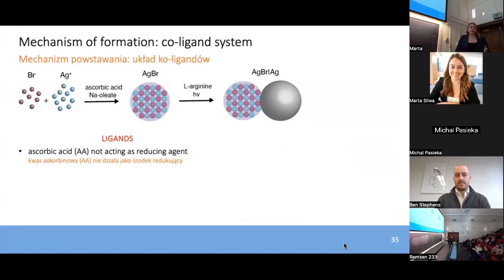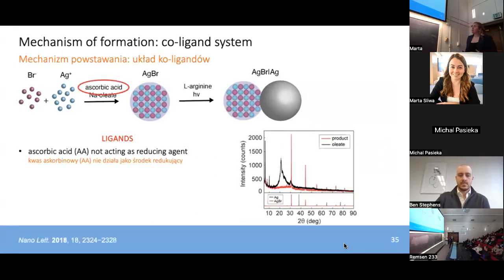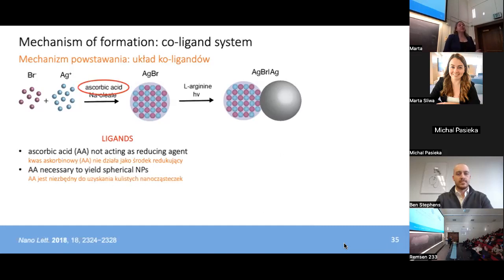So the next puzzle piece that we wanted to figure out was what the ascorbic acid was doing in our synthesis specifically. So in our silver bromide synthesis, ascorbic acid is not acting as a reducing agent, as it commonly does in noble metal nanoparticle syntheses. So again, this is demonstrated by the lack of PXRD peaks corresponding to metallic silver in the samples of these silver bromide hosts. It seems, though, that ascorbic acid is working with the oleate ligands to stabilize the silver bromide nanoparticles and controllably direct their growth to form these spherical host intermediates.